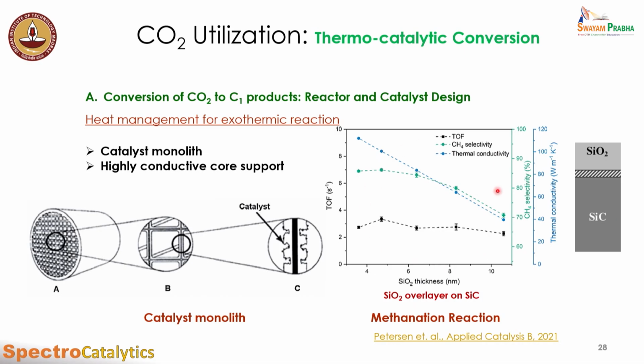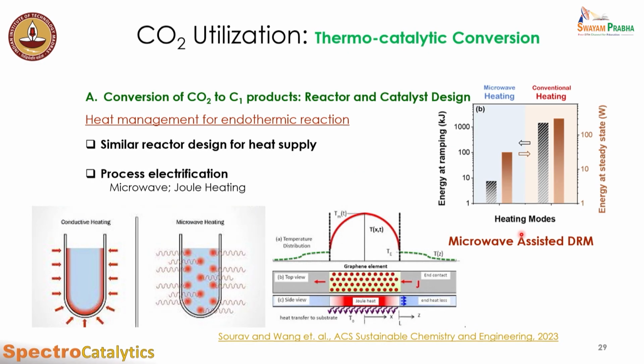Here is an example with different thicknesses of silicon oxide present on silicon carbide for the methanation reaction, and how that affects our reactions. As I increase the SiO2 thickness on the silicon carbide, which is the high thermal conductivity material, the thermal conductivity of the overall material goes down, shown by the blue curve. At the same time, even if activity isn't changing, selectivity towards methane, our desired product, goes down. That's because enough heat isn't being dissipated efficiently from the catalyst, meaning catalyst hotspots form at the molecular or micro level with higher temperature, which promotes the side reaction, the reverse water gas shift reaction, increasing selectivity towards CO.